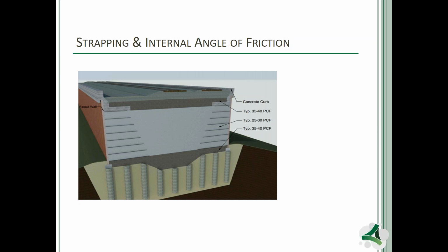From the internal angle of friction perspective, if you're looking at it from a conservative perspective, you're generally looking at 35 to 40 degrees. On a liberal side, you're looking at 60 to 70 degrees. The thing is that it really depends how you look at that wall. Are you looking and designing it as a soil wall, or are you looking and designing it as a concrete wall? I could argue that either way for you, depending on how you want to take a look at it.